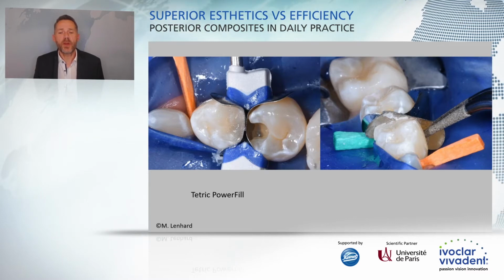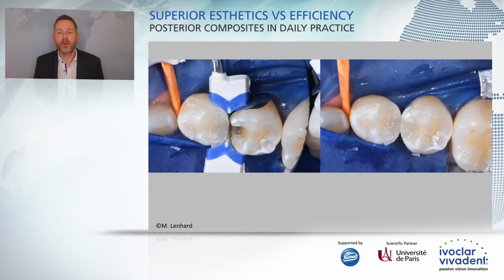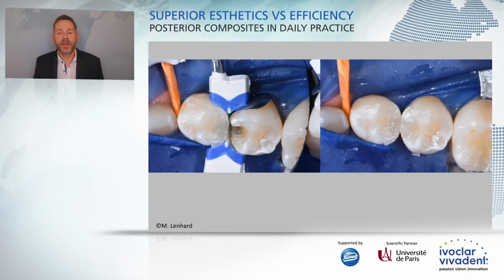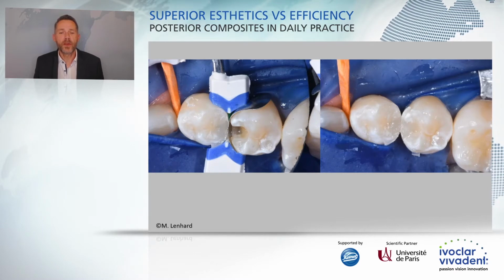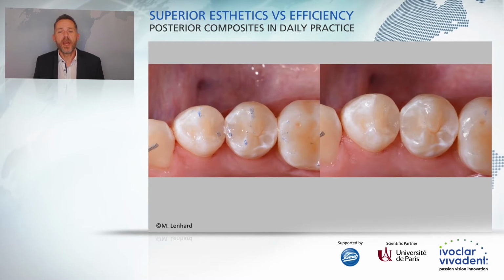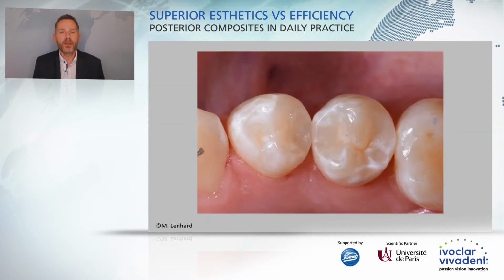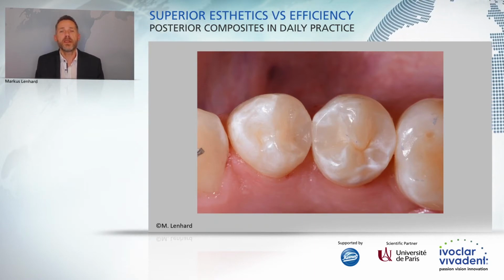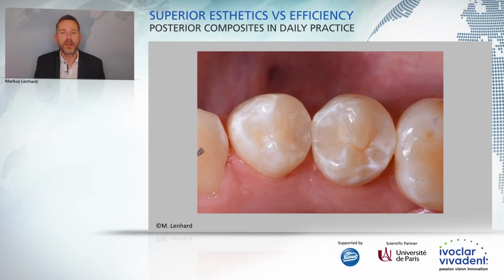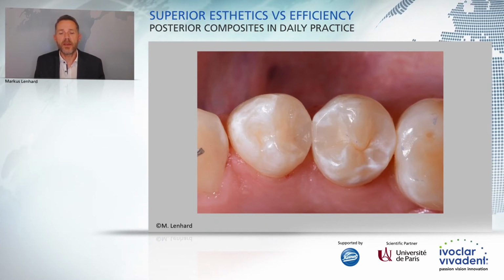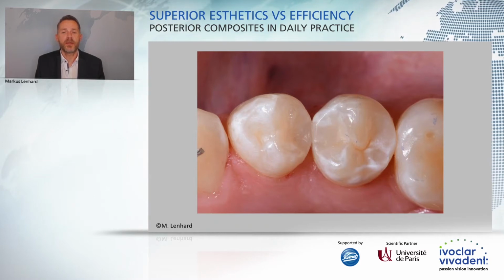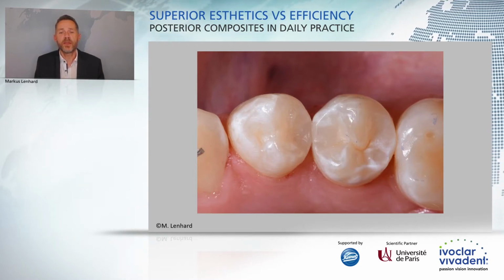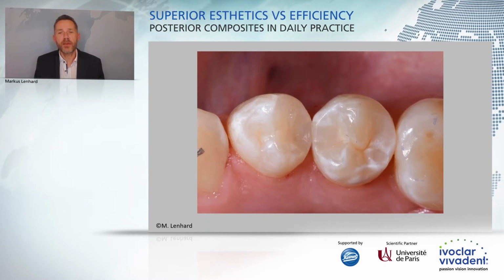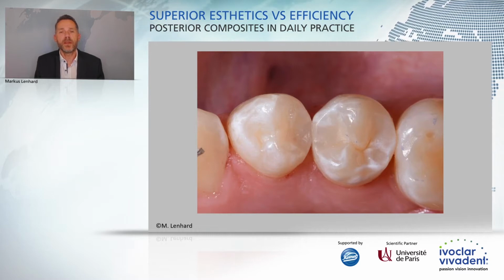And you see that on the first premolar, and then the same on the second premolar, and then on the right-hand side you see the finished restoration after removal of the matrix systems, and finally after polishing. And if we look at this now, we can ask, is this a perfect color match? And it's certainly not. You see that the material is slightly more translucent than the tooth. But will the patient really be able to tell the difference? I would guarantee the patient can't see the difference, and probably you yourself can't see the difference, and you can certainly not see it at speaking distance. On the other hand, you have a very fast, comfortable, reliable way to do a restoration in the posteriors.